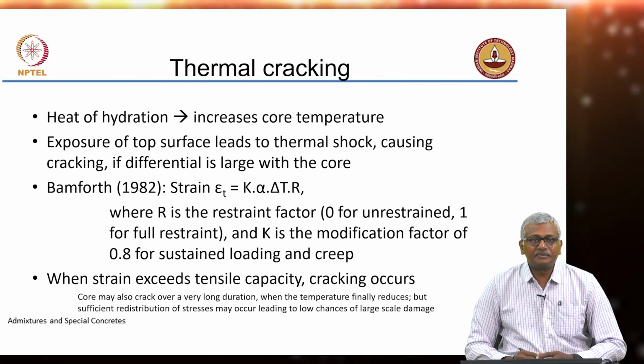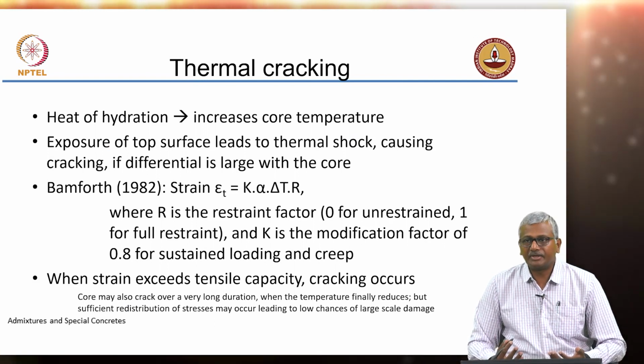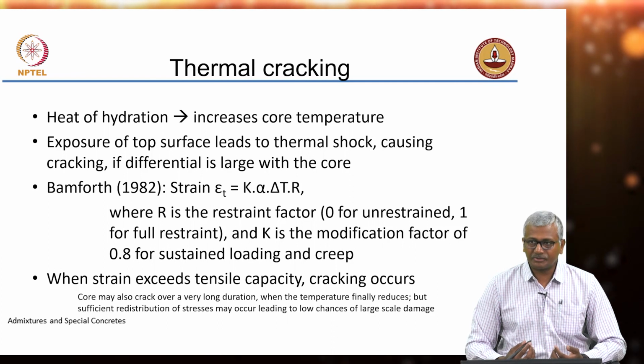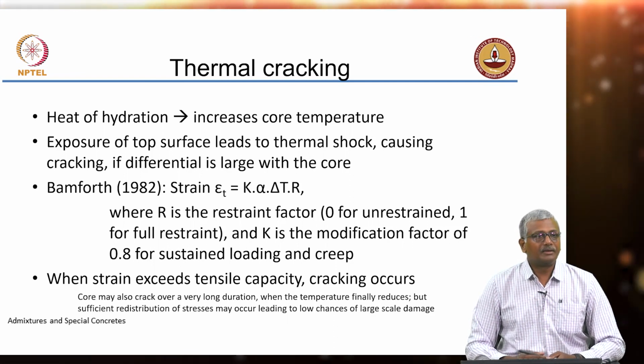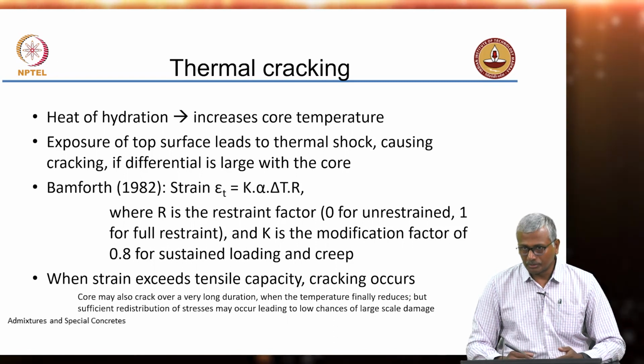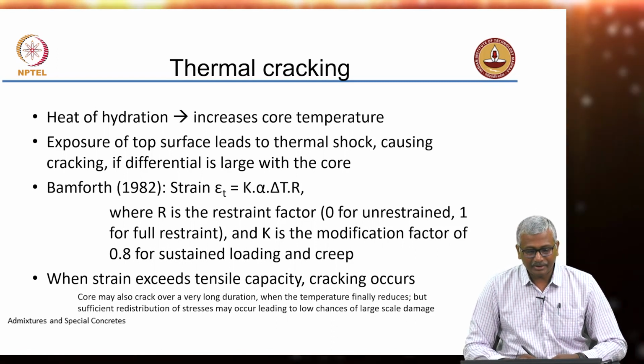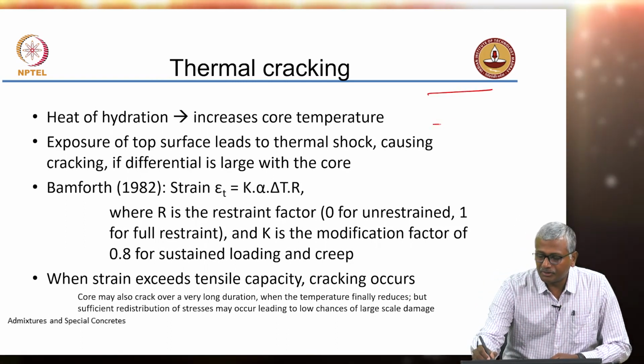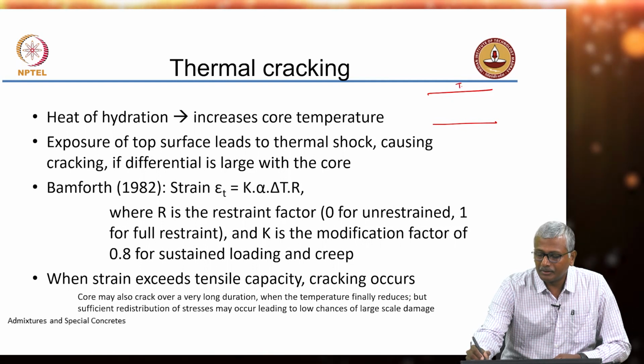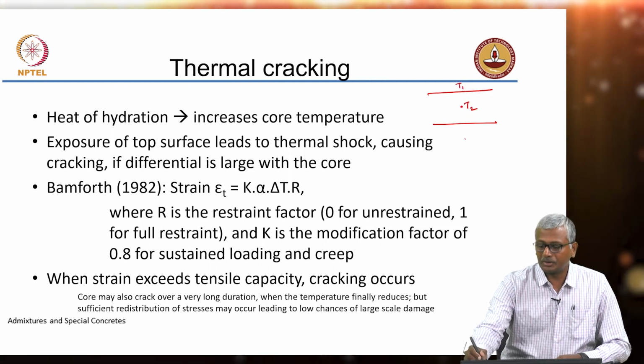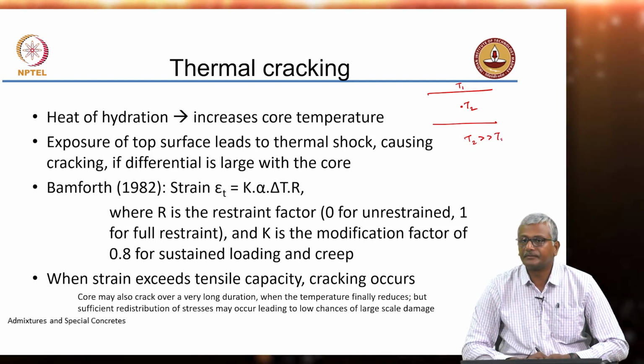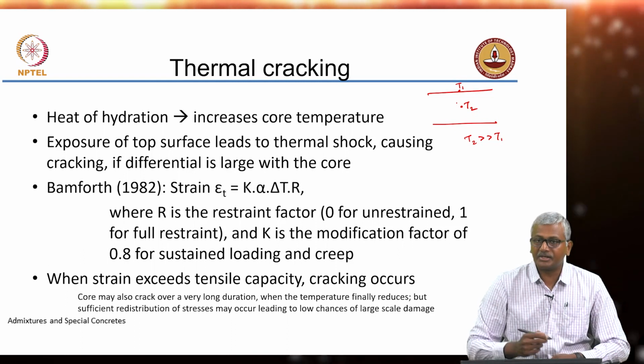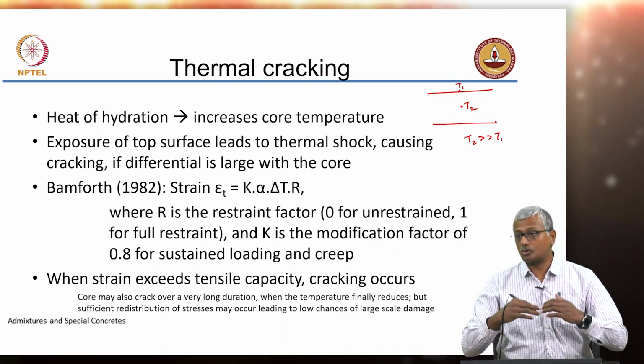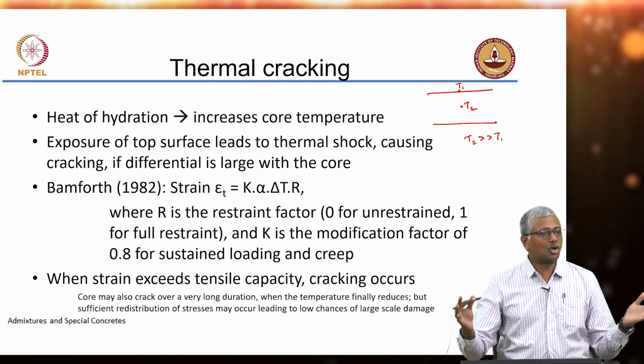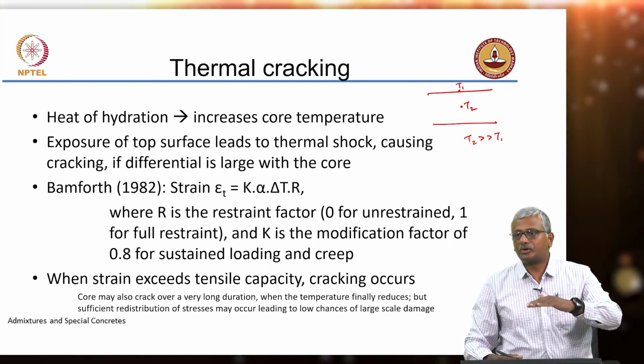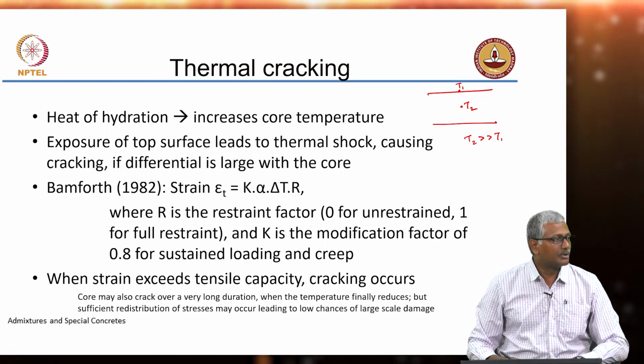So thermal cracking is the problem that we are trying to solve. As we expect, the heat of hydration caused by cement reaction with water will increase the core temperature. The exterior surface is going to cool faster than the core, and this temperature differential will cause cracking. So if you are considering a raft or a slab, the top temperature and the core temperature, so T2 is much greater than T1. The top temperature is going to cool down to ambient conditions quite rapidly if the top is open. You cast the concrete, leave the top open, start curing and stuff, then what happens is your top temperature is very low as compared to your core temperature.